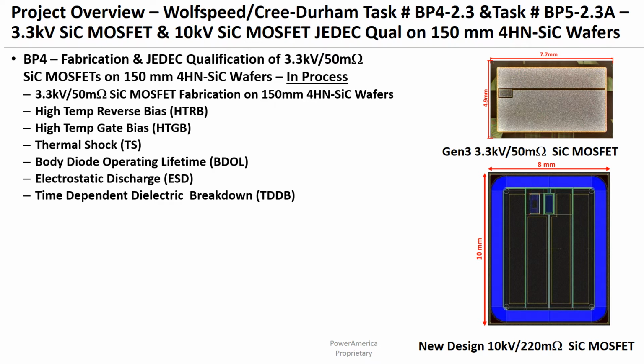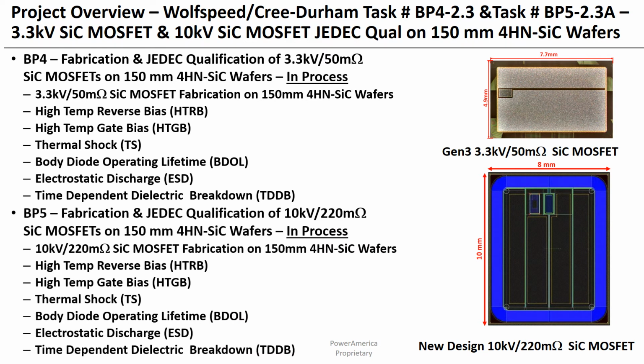We carried out JEDEC qualification on these 3.3 kV silicon carbide MOSFETs. This included HTRB, or high temperature reverse bias, high temperature gate bias, thermal shock, body diode operating lifetime, electrostatic discharge, and time-dependent dielectric breakdown. In addition, we'll be making a presentation on the BP5 project, fabrication and JEDEC qualification of 10 kilovolt, 220 milliohm silicon carbide MOSFETs on 150 millimeter silicon carbide wafers.